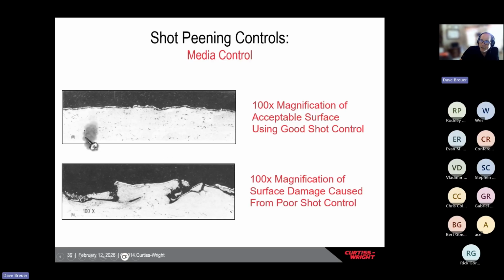Here is a shot peen using high quality media - you'll see no abrupt changes in the surface. Now, if you have softer metal and broken down media, you can see how much you can damage the surface, where these stress concentration sites are probably going to be a future fatigue crack starting at that surface.